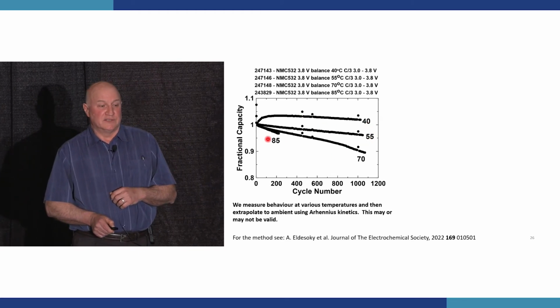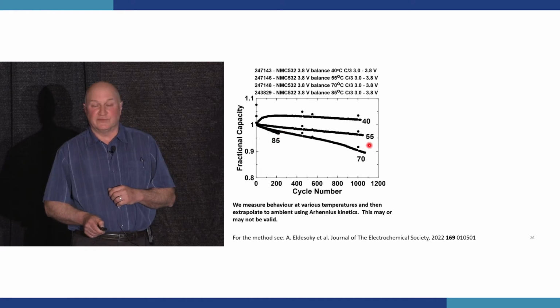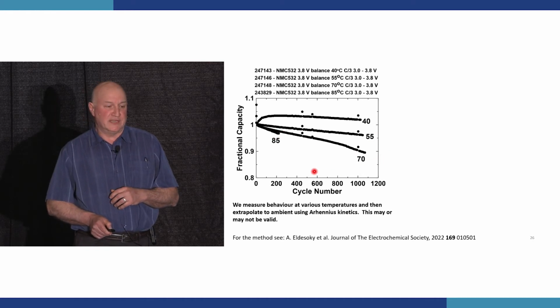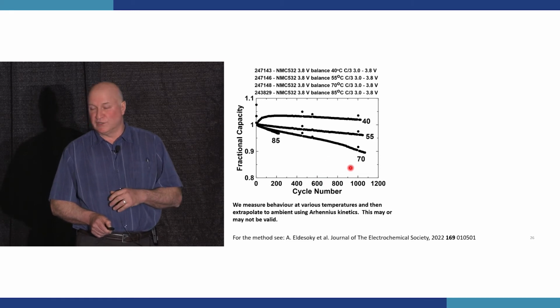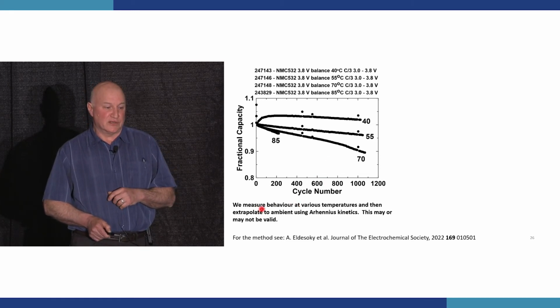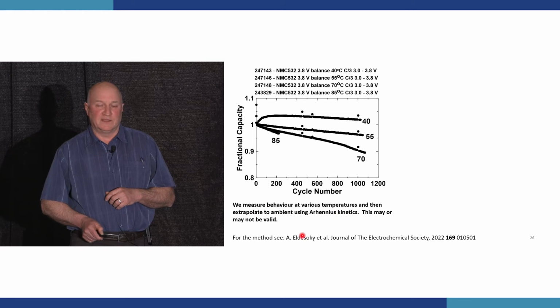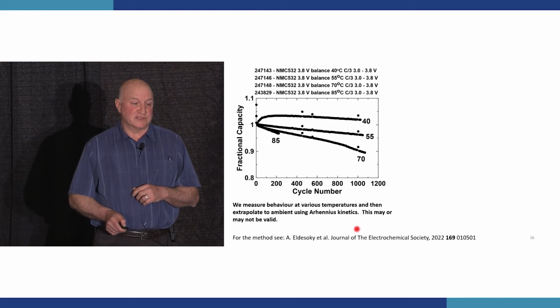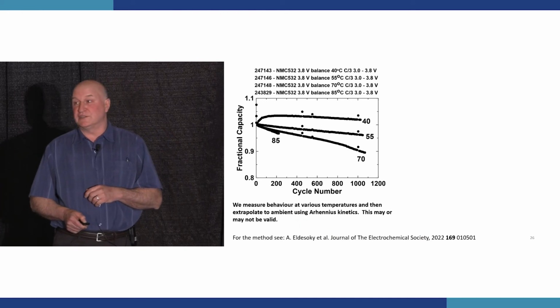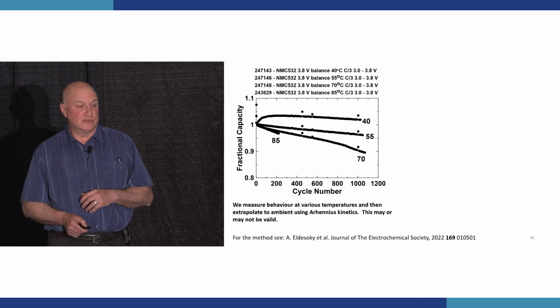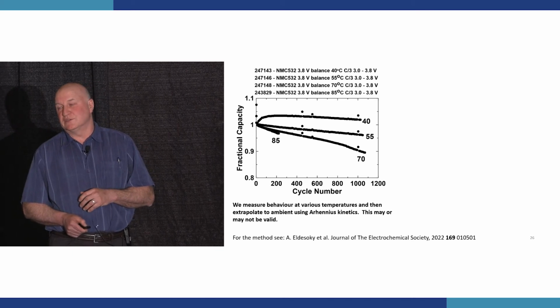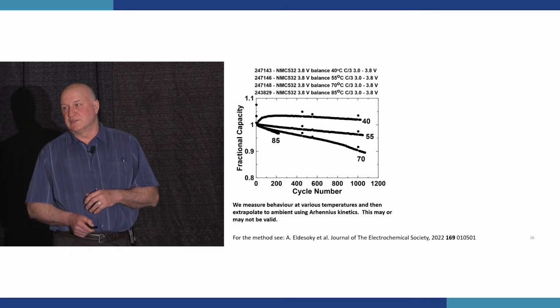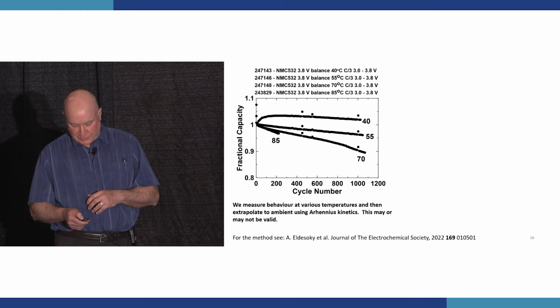So you have to take data at different temperatures, 85, 70, 55, and 40, and then use that data to extrapolate to lower temperatures, and we use Arrhenius kinetics for that. And for the method that we use, you can find it in this particular paper by A. Eldesoky. And this extrapolation may or may not be valid, but it's really the best we can do apart from actually putting them on test for an incredible length of time.